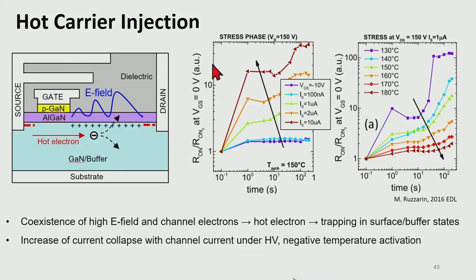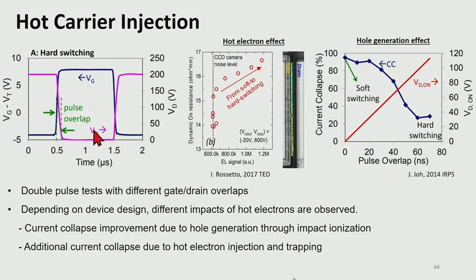This high voltage semi-on state stress setup is useful to study the hot carrier injection effect. But since this is a DC setup, there are several limitations. For example, we cannot use a high voltage and high current at the same time because it can cause severe self heating. So as another option, we can use a double pulse measurement. By controlling the gate and the drain voltage signals separately, we can create an overlap time. During this overlap time, the device turns on under high drain voltage, so a lot of hot carriers can be generated, but we don't need to worry about severe self heating because this overlap time is very short.